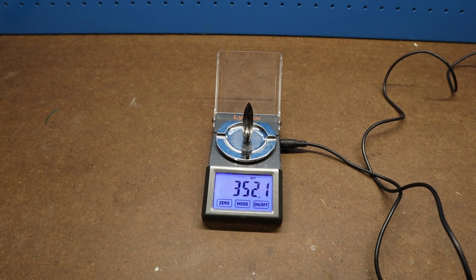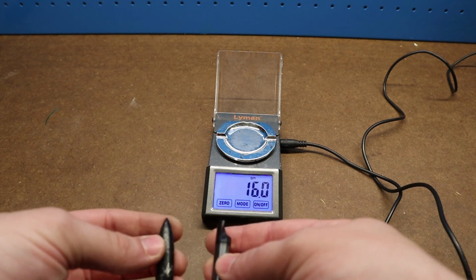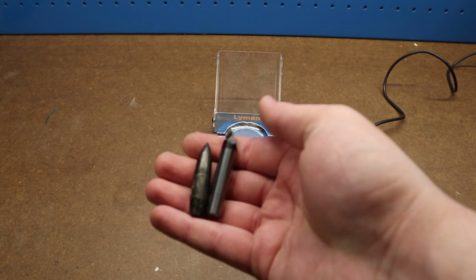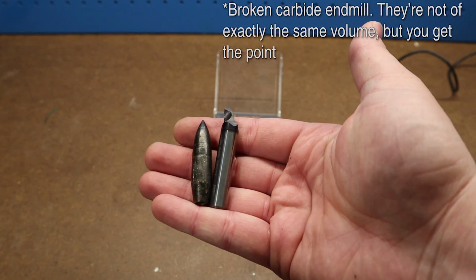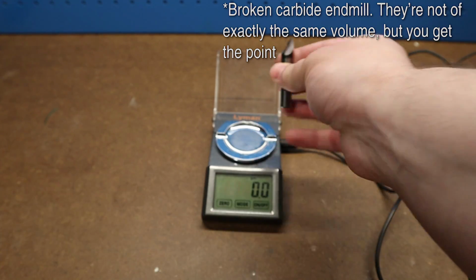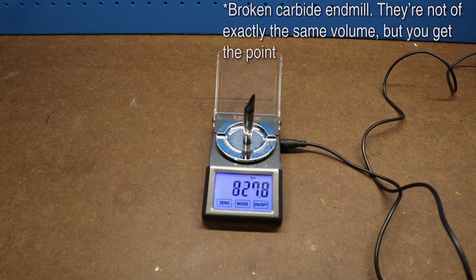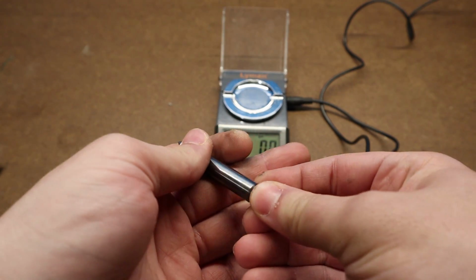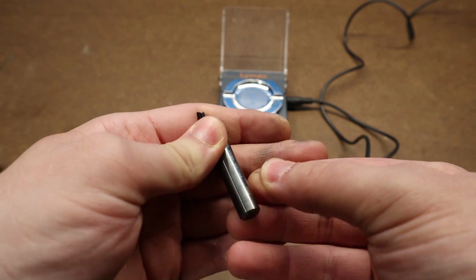And what about tungsten? Well, same reasoning applies. It has about the same density as uranium, or slightly less in case of cemented tungsten carbide. In any case, a penetrator of a given size made of a tungsten-based material would weigh at least 80% more than if it was made out of steel, so you can easily find out if a penetrator is made of tungsten simply by comparing its weight to its volume. Another way is using a magnet. Tungsten is non-magnetic and its cemented carbides are just slightly magnetic.